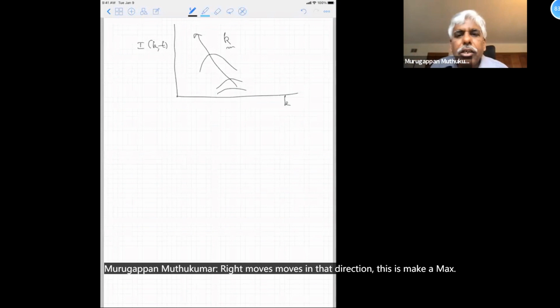Now what does that mean? That means that the fluctuations, if I take the fluctuation to begin with, will be like this. Then I have very strong fluctuations like that. So here this is my lambda 2, and here it's only lambda 1. This is for T1, this is T2. The fluctuation wavelength becomes very large. That means K becomes small. That means bigger droplets are being formed, bigger domains are being formed.